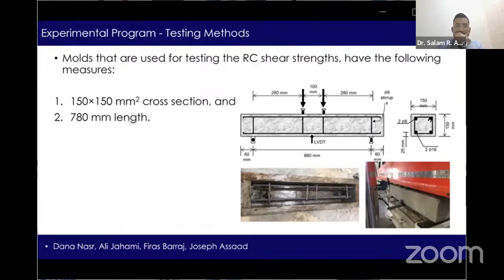Let's talk now about the testing methods. So our purpose was to determine the hardened density, the compressive strength, the splitting tensile strength, the modulus of elasticity, flexural strength, and shear strength. The molds that are used for testing reinforced concrete shear strength have the following measures: 150 by 150 millimeter square cross-section and 780 millimeter length. The 28-day simply supported beams were subjected to 2-point symmetrical loading. The vertical load was distributed on 2 points acting on the beam surface through rigid steel supports. And the load was applied gradually at a rate of 0.2 kilonewton per second. Finally, the midspan deflection was recorded using an LVDT, or linear variable differential transformer, placed on the tension side as shown on the figure in this slide.